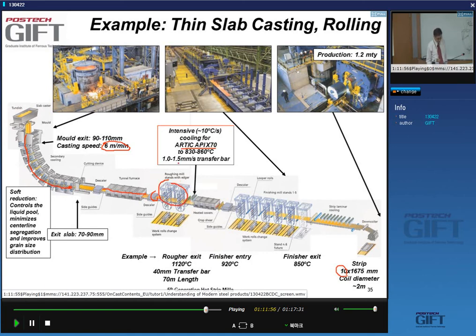The bar here, the thickness is again on the thicker side, around 100 millimeters. Towards the end of your caster here, you have again this soft reduction, which controls the liquid pool that's left inside in the center of your strip, and as you squeeze it, you limit center line segregation and also the grain size distribution eventually. So you have a thicker slab here. It goes through a tunnel furnace to equalize the temperature.